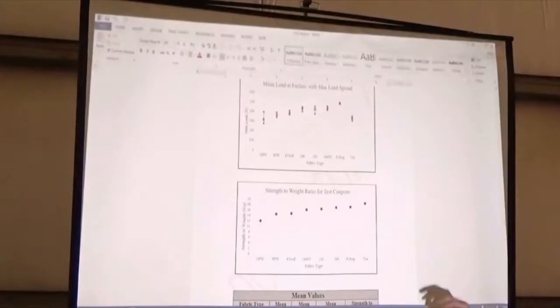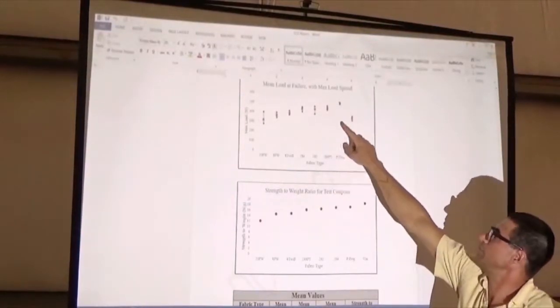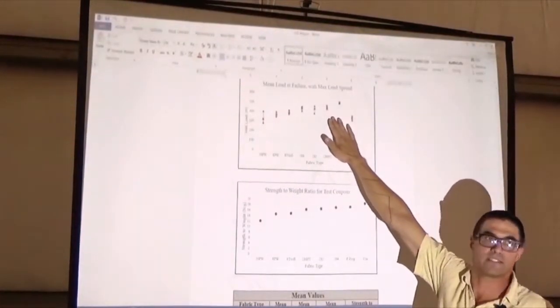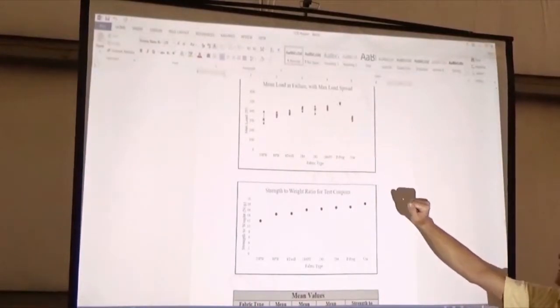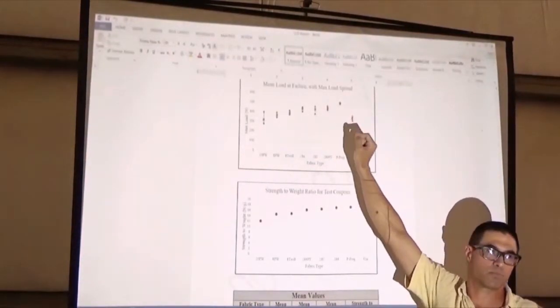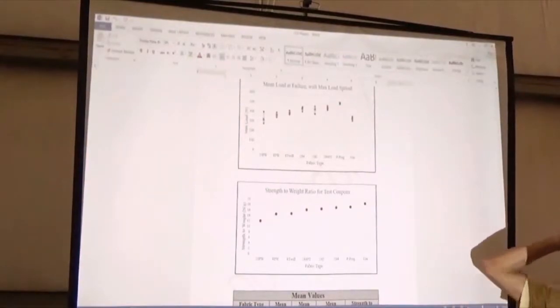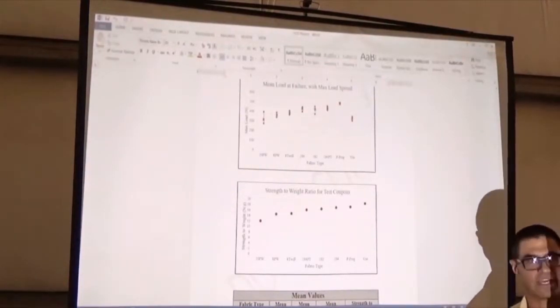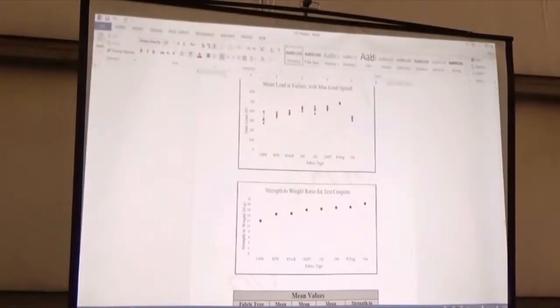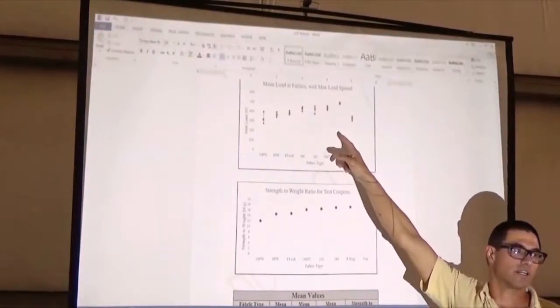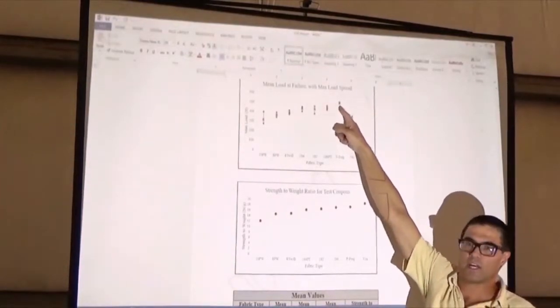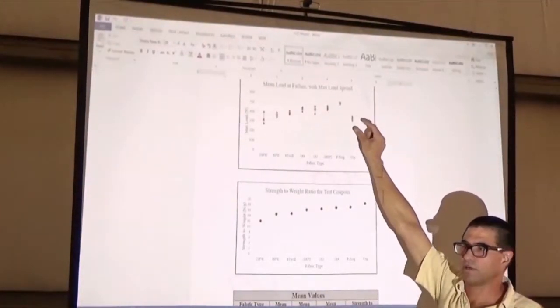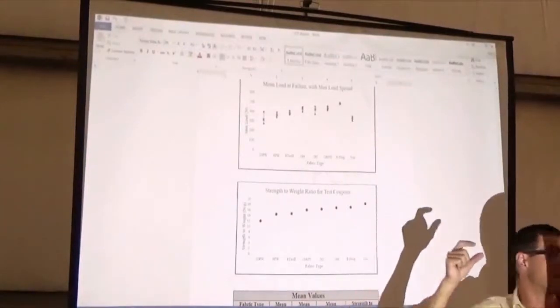So if we come back and look at these results, you'll see that the prime text was the best of the wet lay fabrics, and then the pre-preg, we also did a pre-preg. There's actually some pre-preg that I think Paolo used on, I don't know if you used it on your project or the X57, but yeah, it was X57 pre-preg, so they gave me some and I did a test. And it was by far the strongest, and if you look at the error bars, not the error bars, the spread of the results, it's very tight.